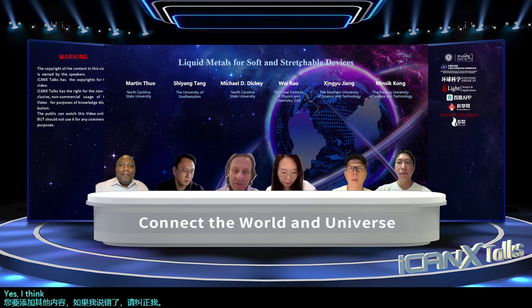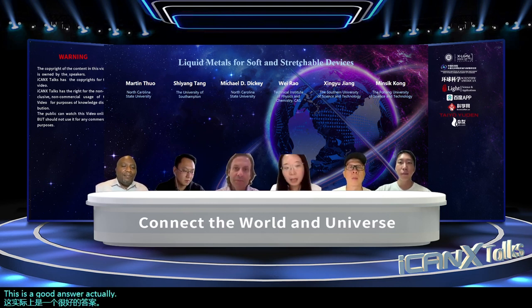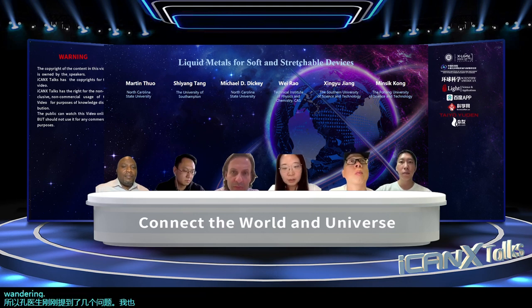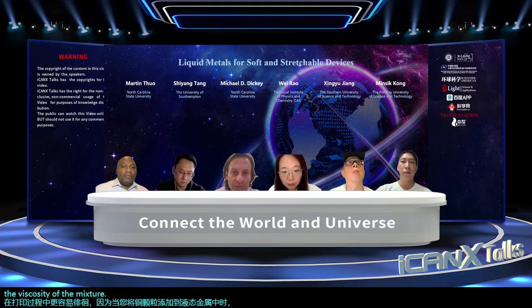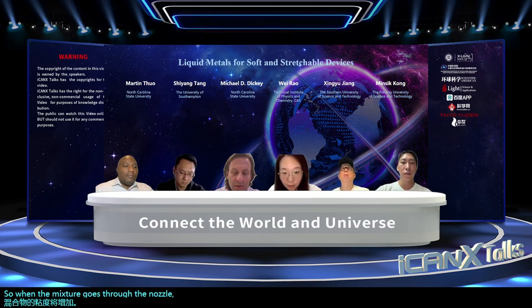I think it's a good answer, actually. I'm also curious about the particle work. Dr. Kong just mentioned several problems. During the printing process, when you add the copper particles into the liquid metal, the viscosity of the mixture will increase. So when the mixture goes through the nozzle, with the resistance, is there any separation between the copper particles and the liquid metal, the substrate?